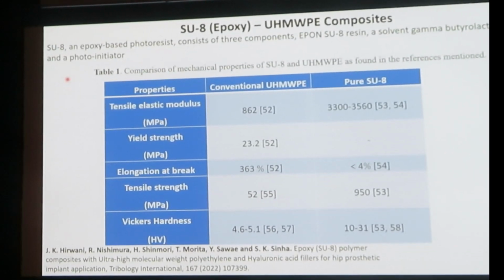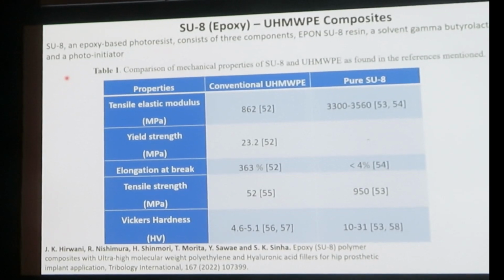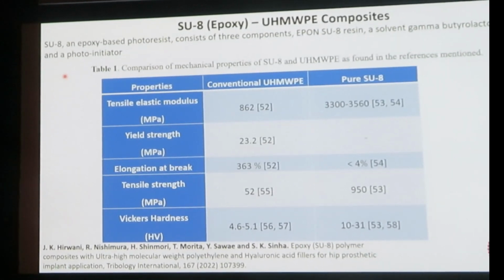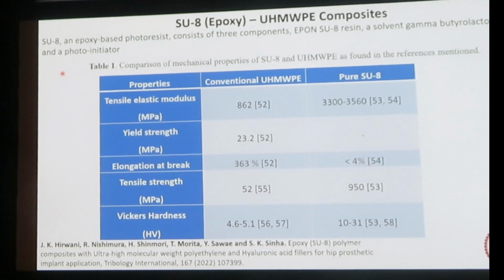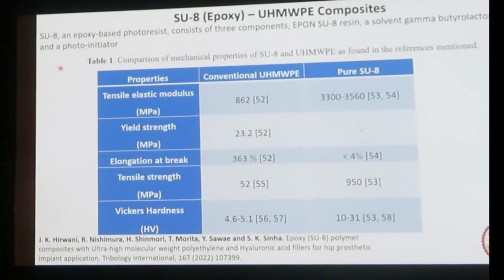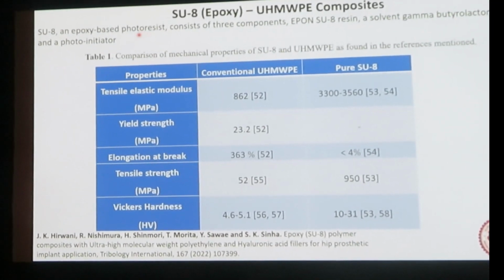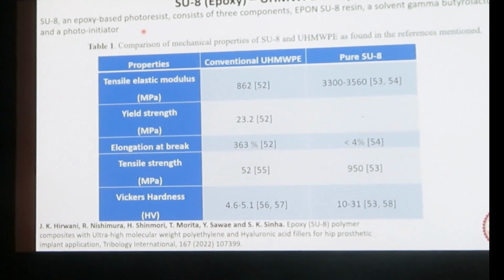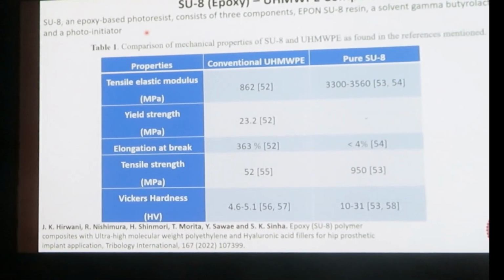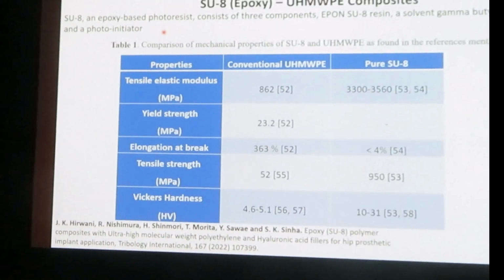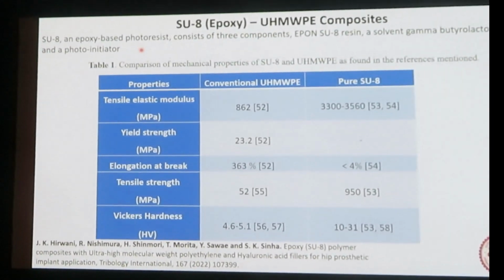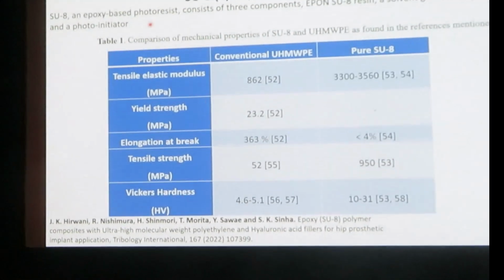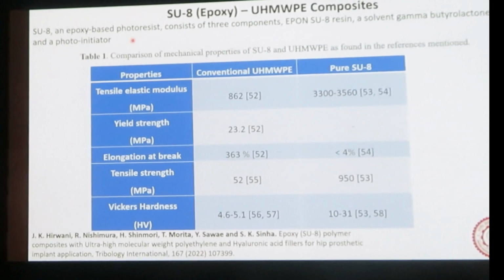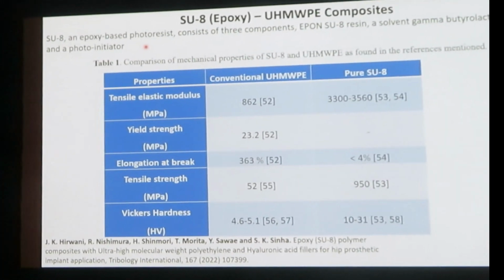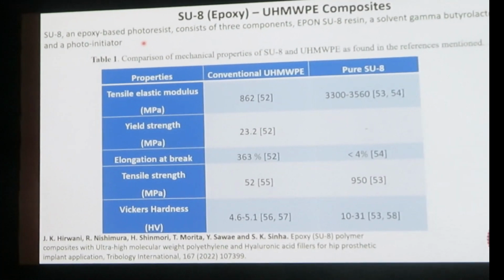In this kind of material, the more you add things, the more toxic you will make it. So using a UV curable polymer might help, but finally we found that UV curing was not a good idea because the mechanical property was not suitable. So we did use some hardeners in a small quantity, but then we conducted a biocompatibility test and it passed.